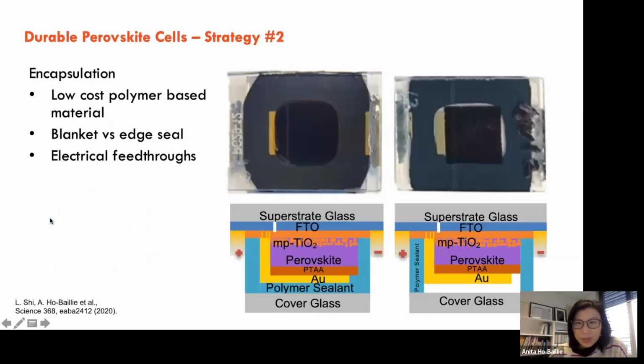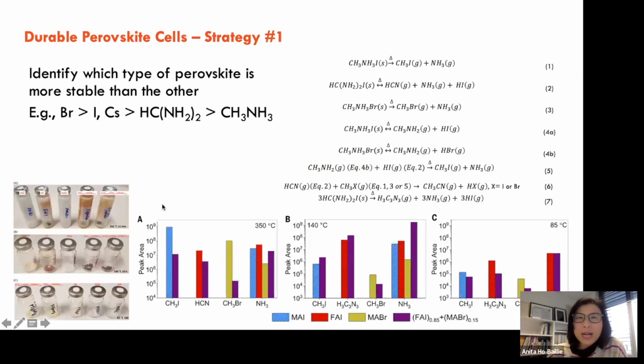And I'll talk about strategy later. By looking at what comes out, what the products are, what the signatures are, we're able to identify the degradation reactions. And we are able to identify which component in the perovskite is more stable than the other. So if you remember metal halide perovskite, we found the halide bromide is more stable than iodide.